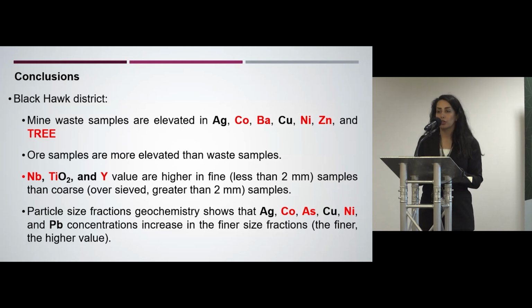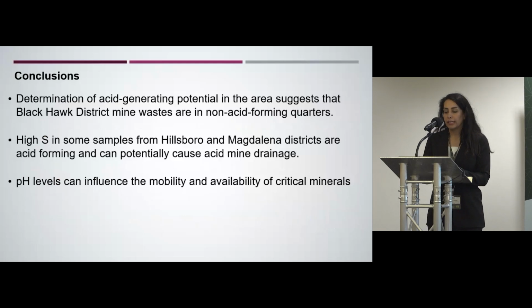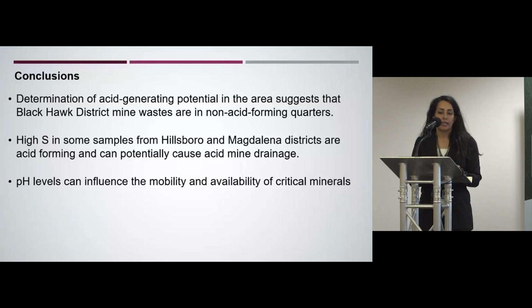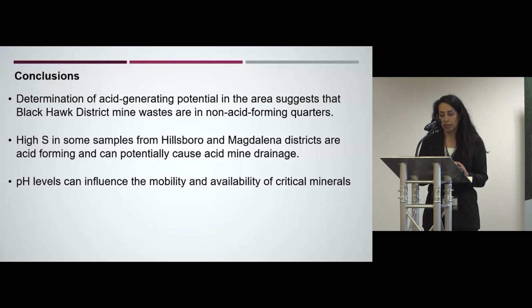And the particle size fraction geochemistry showed that the finer the sample, the higher the concentrations of silver, cobalt, arsenic, copper, and nickel. And determining the acid generating potential showed us that our Black Hawk mine waste samples are in the non-acid forming quarter, which means that we can use them for further purposes, such as backfilling materials. But some samples from Magdalena district, as well as the Hillsboro district, are acid forming and can potentially cause acid mine drainage.